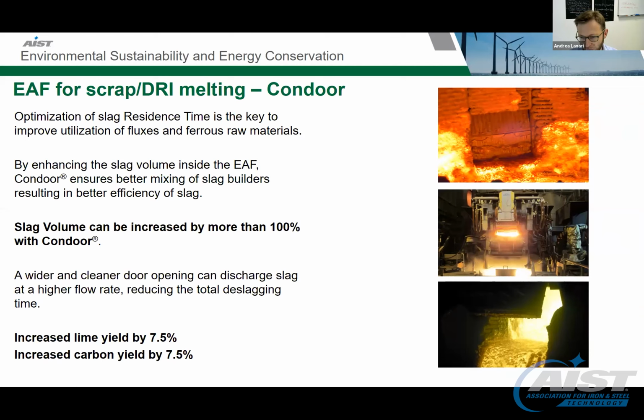So with this solution, with the automatic slag door, we can actually seal the furnace and keep all the slag inside the furnace for the time that we need. And this will bring, of course, saving electricity, saving electrodes, but by far more important, will increase the yield of the DRI melting. Okay, so we'll increase the yield of DRI to liquid steel. And also we are going to lose by far less material in terms of carbon, in terms of lime, because they're going to have more time to react inside the electric arc furnace. This is already in operation in many plants that are working with scrap, but also with DRI.